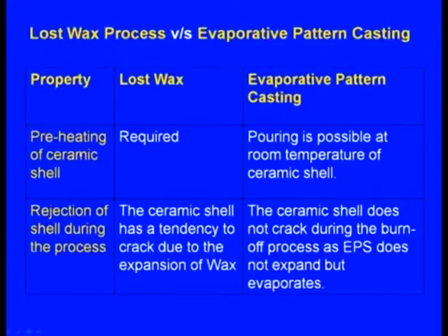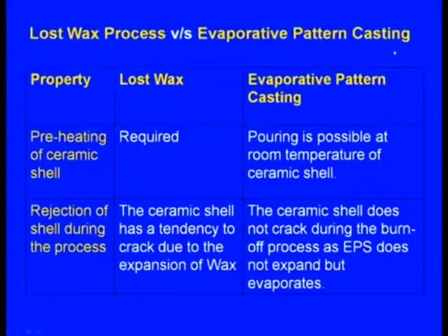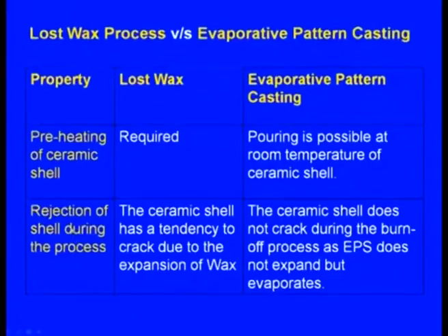Next one, preheating of the ceramic shell. In the case of the lost wax process, it is required. Sometimes what happens is that during preheating the ceramic shell can crack, whereas in the case of the evaporative pattern casting process, pouring is possible at room temperature, with no need for preheating the shell.